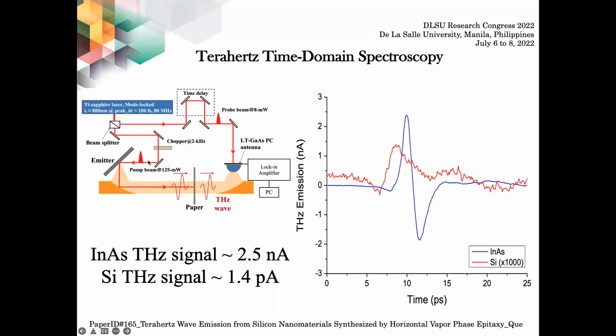To verify its terahertz emission capability, the baked silicon nanowire sample was placed in a terahertz time domain spectroscopy setup and was also compared with a P-type indium arsenide terahertz emitter, which is known as the best bulk semiconductor terahertz emitter to date. A mode-locked titanium sapphire laser was used to excite the surface of the emitters. Results showed that the silicon nanowire sample emits terahertz waves, as can be seen in this figure. The terahertz signals from indium arsenide and baked silicon nanowire are 2.5 nanoamperes and 1.4 picoamperes respectively.